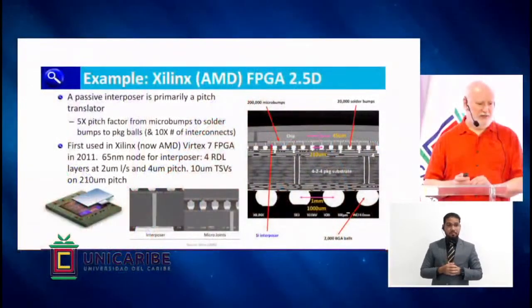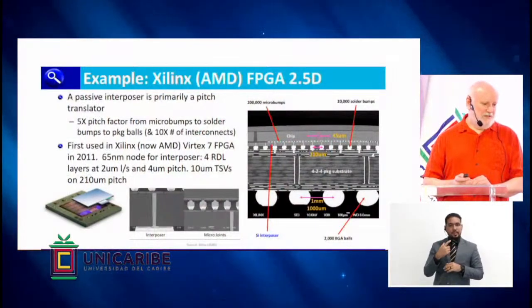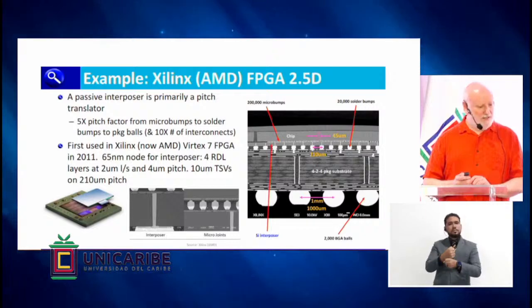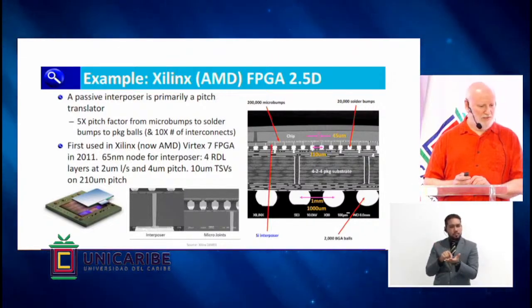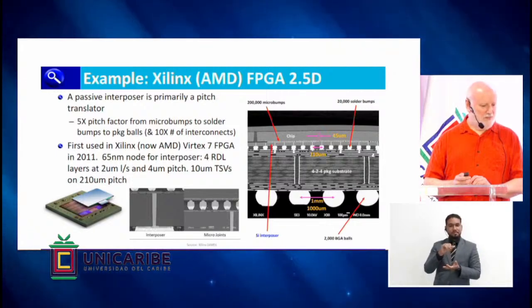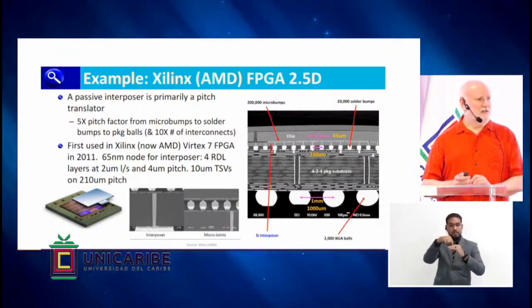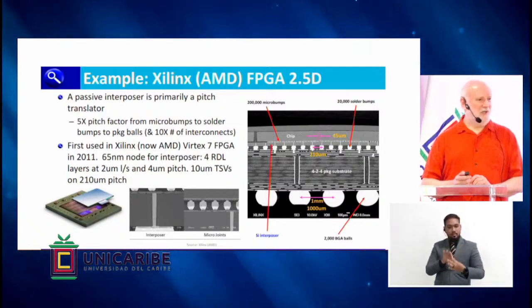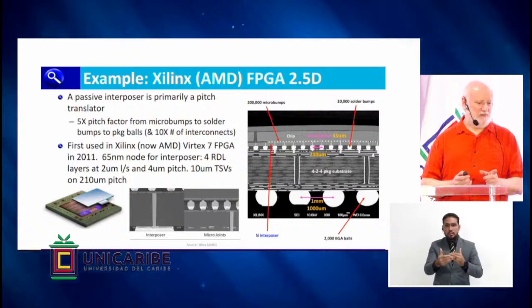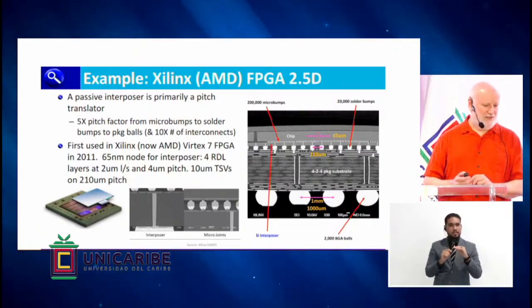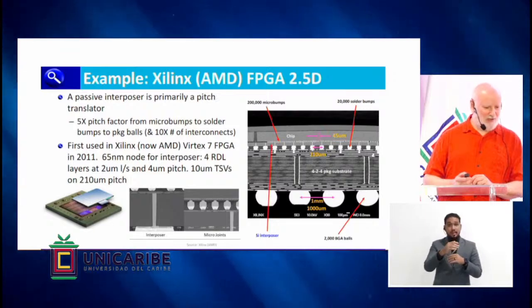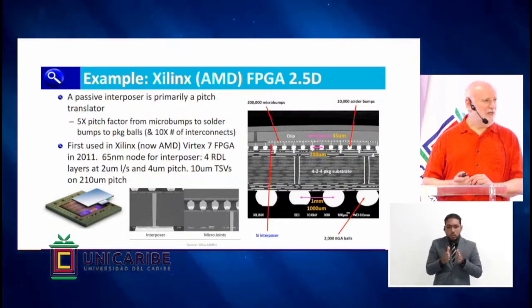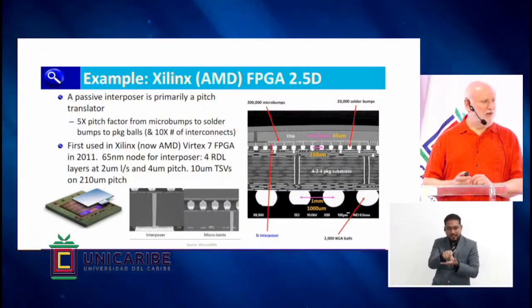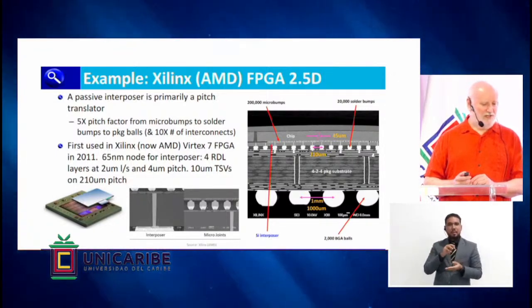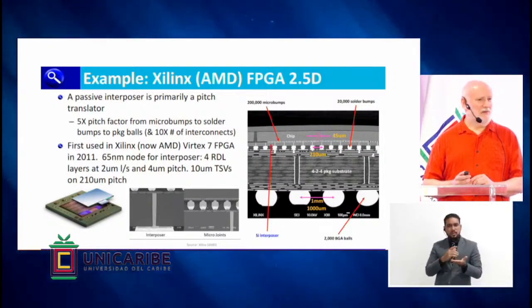This was maybe one of the first commercial products that came out, I think in about 2010, 2011, as listed there. It shows the concept where the chip is sitting on the interposer, and the interposer is sitting on the substrate. Again, it's this requirement to go from very fine pitch to wider and wider pitch, and we're doing it twice in the package here. You're starting with micro bumps on the chip at 45 micron pitch, then on the bottom side of the interposer we're at 210 micron pitch, and then at the bottom side of the package substrate we're at 1,000 micron pitch.